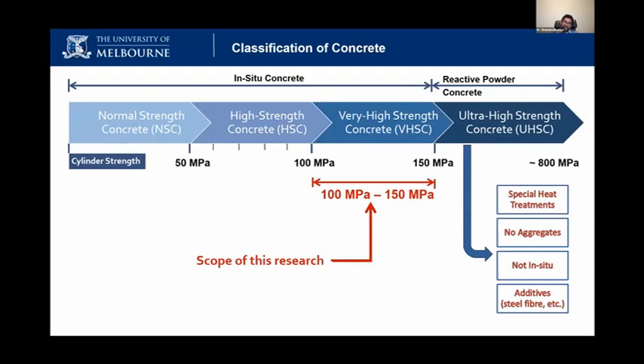So this research that I'm going to present is more on how to achieve strength between 100 to 150 megapascal using economical mix designs. Economical mix designs mean using blended cement. Jan especially mentioned that INSEE also has a blended cement. So I think this presentation will be a good example to show how blended cement can be used sustainably and cost efficiently to produce very high strength concrete, around 100 to 150 megapascal. Using a high amount of cement is not possible because of the heat of hydration, so we have to blend it to reduce the heat of hydration as well as the cost of the mix.